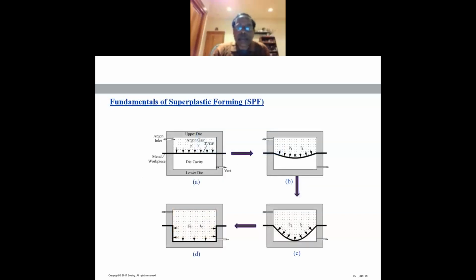Here is a schematic representation I'm showing you. In superplastic forming, the metal workpiece is placed between the upper and the lower die. The material is brought to the plastic forming temperature by increasing its temperature, and then argon gas is applied into the cavity under pressure. Gradually, under pressure, the material is completely in the superplastic state and forms from this shape to this shape, and finally to the final cavity of the die block.